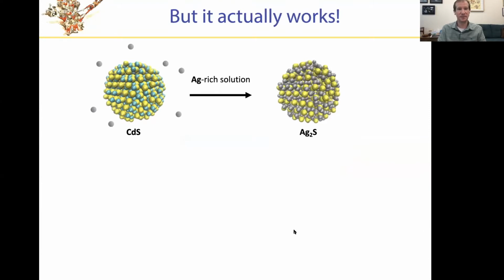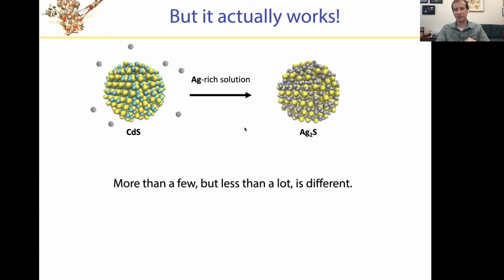And sometimes it happens as simply as immersing one of these nanostructures in a solution that is rich in the incoming ion, in this case, the silver ion. If you just put cadmium sulfide ions in an appropriate solvent with silver ions, go and get coffee, you come back, and quite literally what's happened is that every cadmium ion has been exchanged with a pair of silver ions, and the overall structure and integrity of the crystalline lattice has essentially been preserved. And this is a stark reminder that this nanoscale is really different. It's more than a few, but less than a lot.